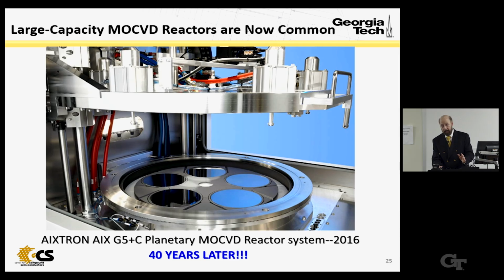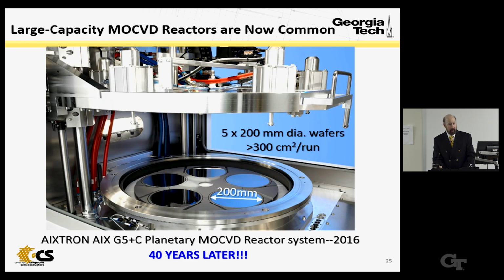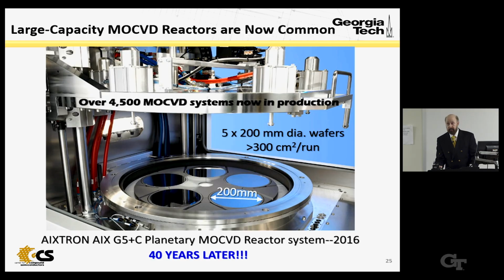Well, today, large capacity reactors like the ones I showed you are common. This is an Aixtron AIX G5+C, first developed in 2016, 40 years later. It has 5 200 millimeter diameter wafers per run. It's greater than 300 square centimeters of epi per run with high uniformity and high yield. So they've exceeded my predictions pretty well. In fact, there are now larger reactors in production. There are estimated to be about 4,500 MOCVD reactors in production today, a lot of them in China.